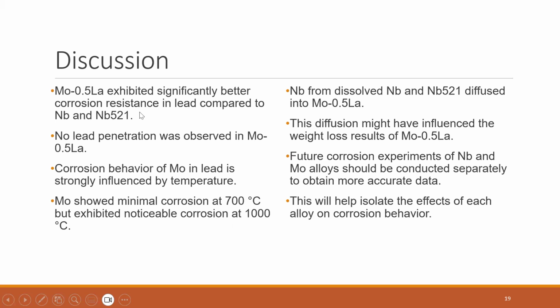Molybdenum exhibited significantly better corrosion resistance in lead compared to niobium and niobium alloy. No lead penetration was observed in molybdenum alloy. Corrosion behavior of molybdenum in lead is strongly influenced by temperature. Molybdenum shows minimal corrosion at 700 degrees Celsius, but exhibited noticeable corrosion at 1000 degrees Celsius.